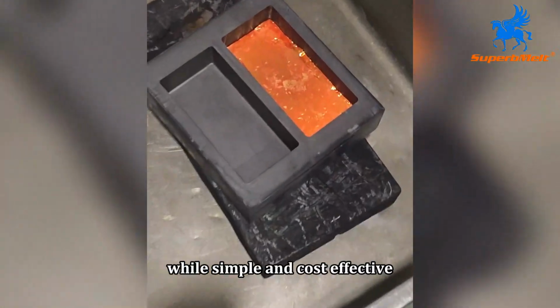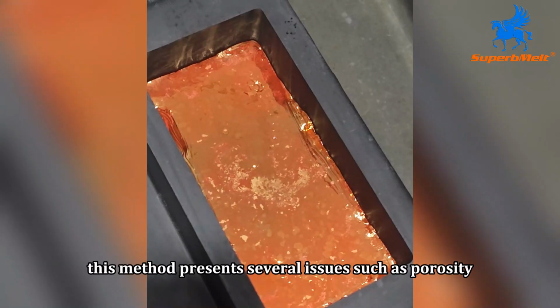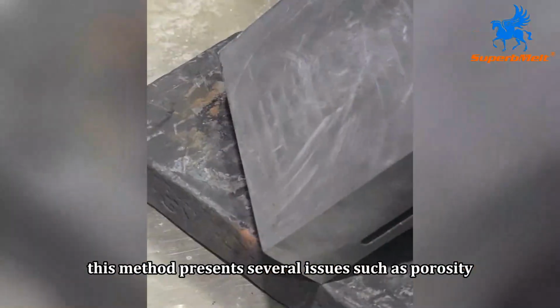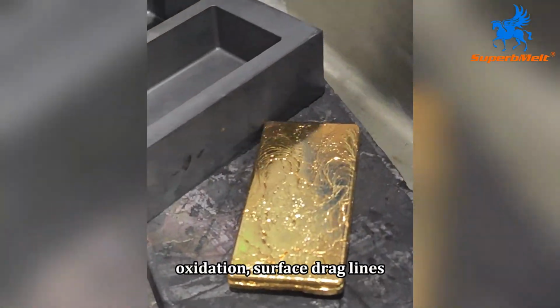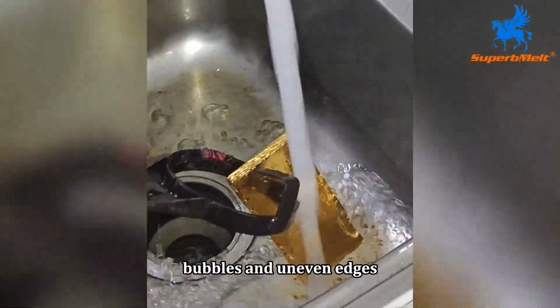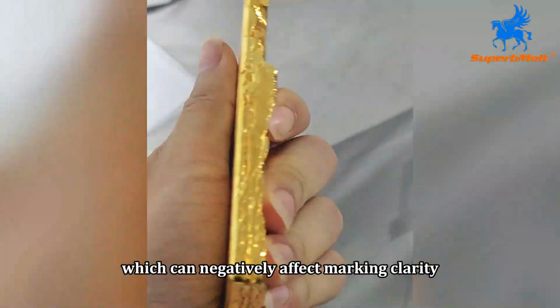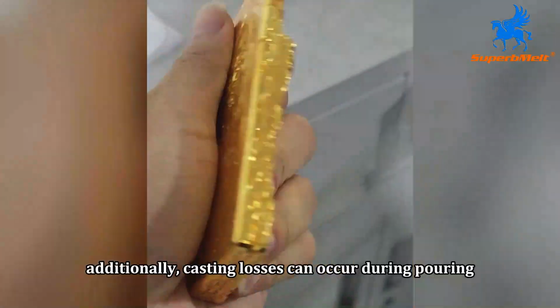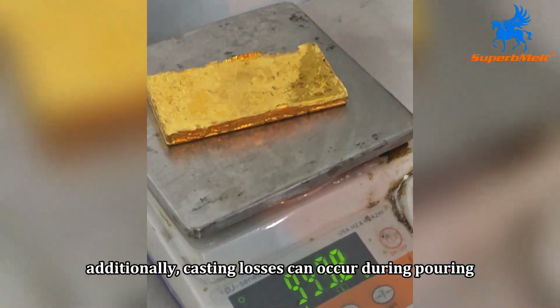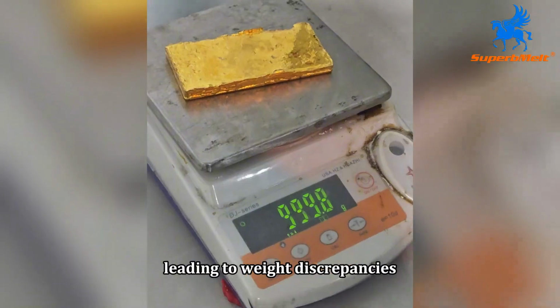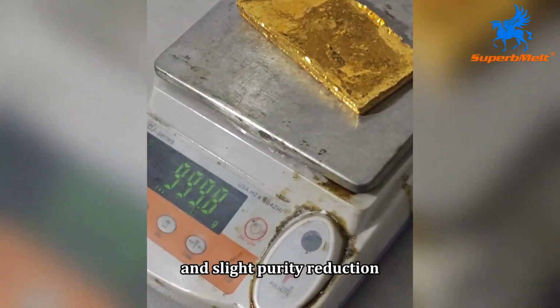While simple and cost-effective, this method presents several issues, such as porosity, oxidation, surface drag lines, bubbles, and uneven edges, which can negatively affect marking clarity and customer inspection. Additionally, casting losses can occur during pouring, leading to weight discrepancies and slight purity reduction.